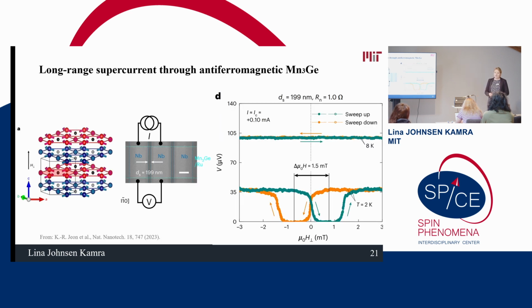Now, in the end, I just wanted to mention this paper that I found quite interesting, because even though there have not been so many experiments on this topic yet, there was this experiment on a three sublattice antiferromagnet where they showed that under an out of plane magnetic field, where they tilt all the sublattices a little bit out of plane, you can get very long range triplet currents when the distance between the two superconductors in the Josephson junction is very, very long.